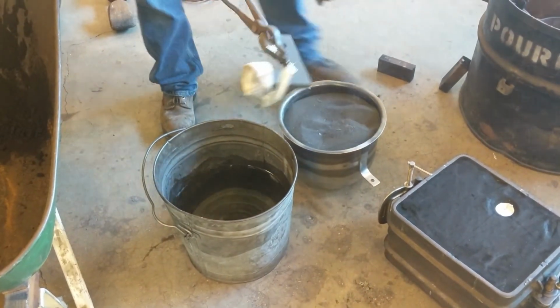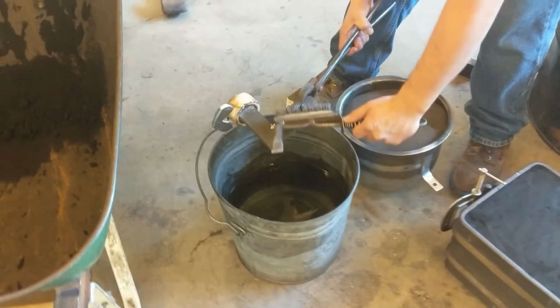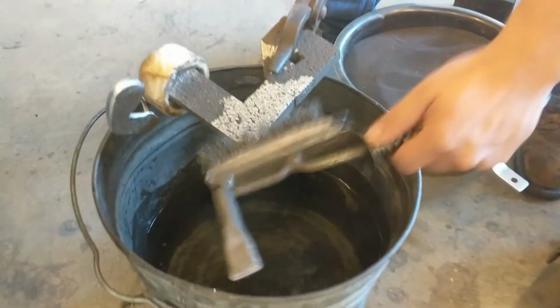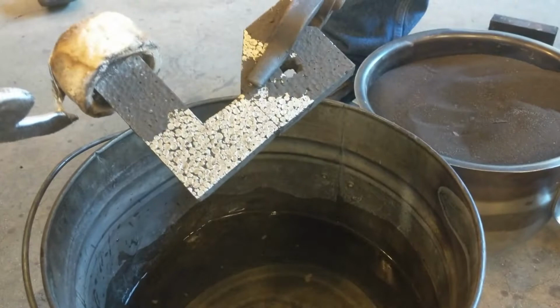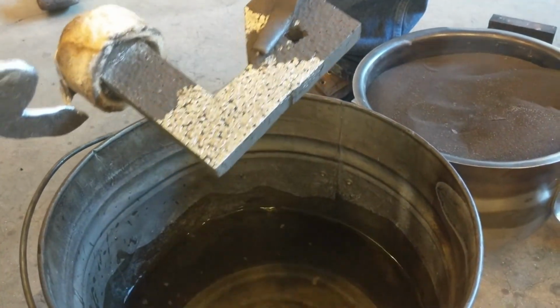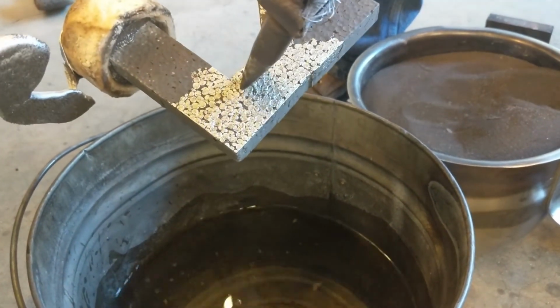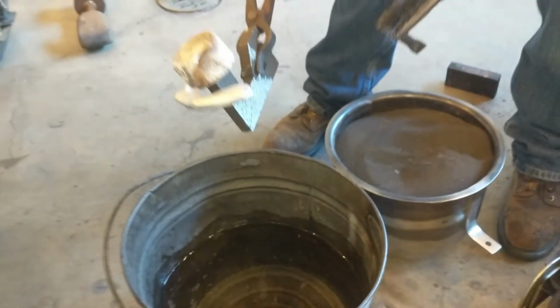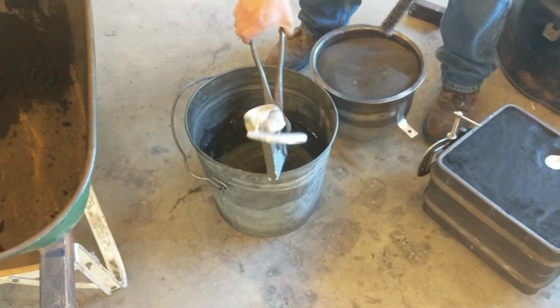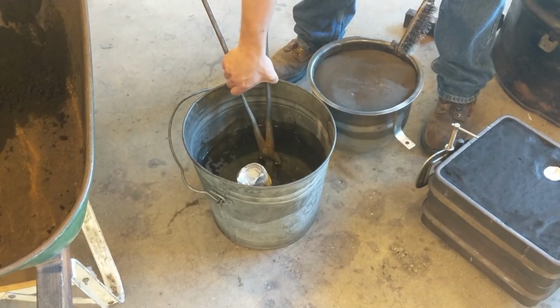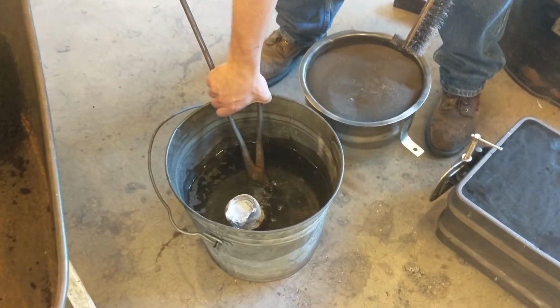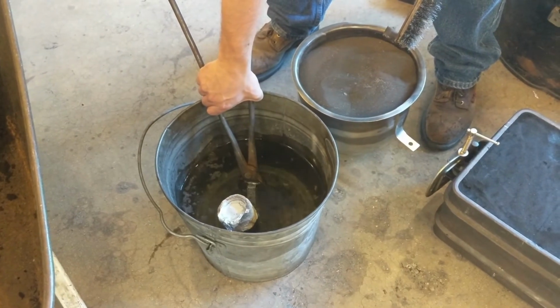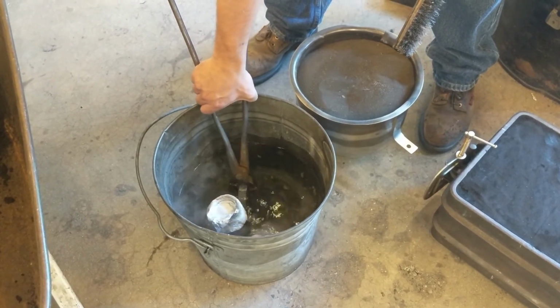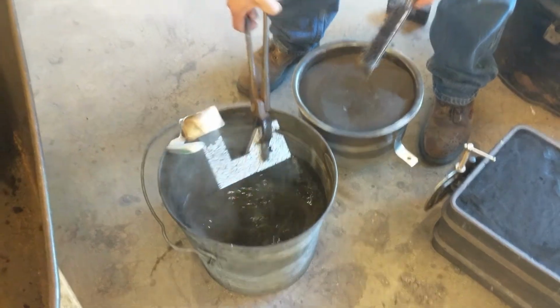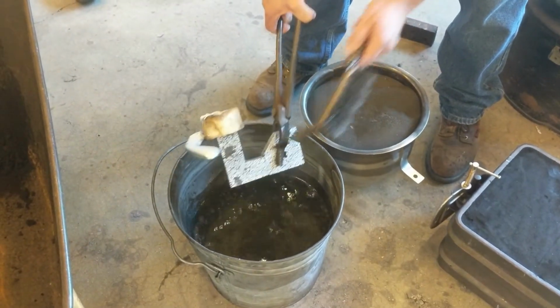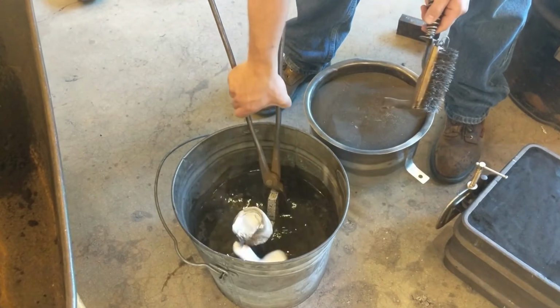Now before I quench this, if you look carefully, you'll see that once I brush that refractory coating off, you can see the aluminum, and the surface finish is so good that you can still make out the little pellets of polystyrene foam. So it's a high resolution casting process and has a lot of advantages over the green sand process. We'll get that cooled off a little bit. And that can move on to being sectioned.